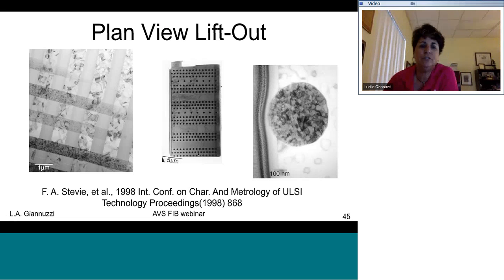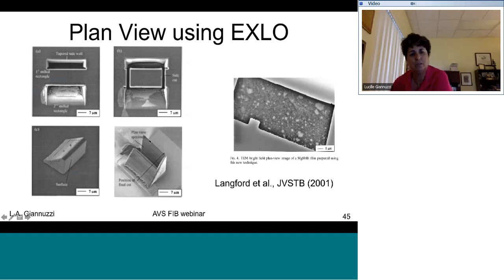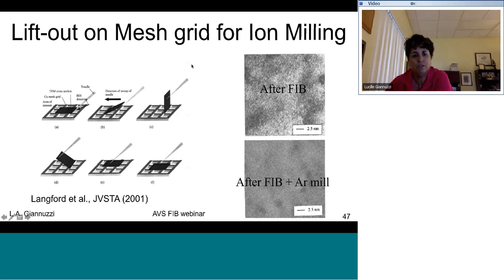So you can do plan view ex situ lift out, not a problem, by just positioning the sample into the FIB at 90 degrees and doing a plan view type of sample. Here's something that Richard Langford did years ago by using ex situ lift out, just cutting a big trench, using it to manipulate the sample upright, putting it back in the FIB to thin this sample, and then cutting it free and using the probe to place it on a carbon grid. Richard Langford also showed that you can lift out a sample and put it on a smaller grid opening sample, and then argon ion mill one side, and then flip it over and argon ion mill the other side to reduce 30 kV FIB damage.